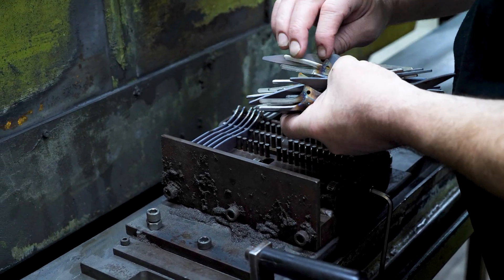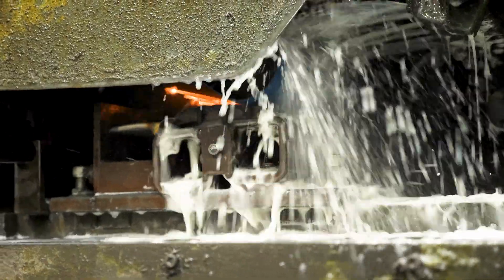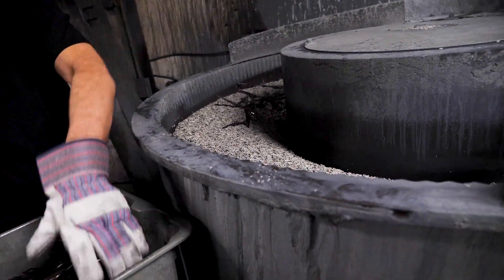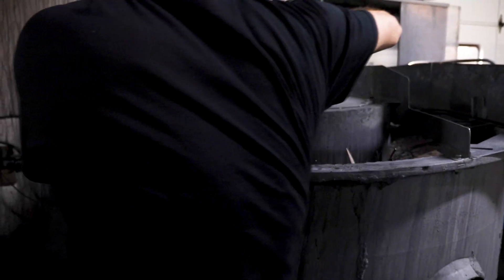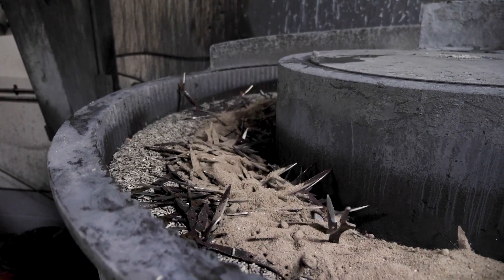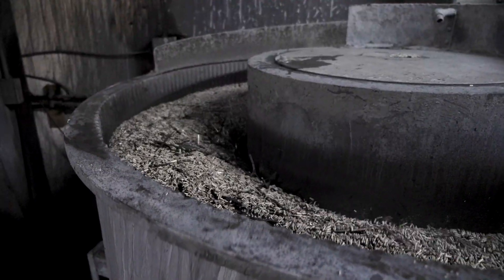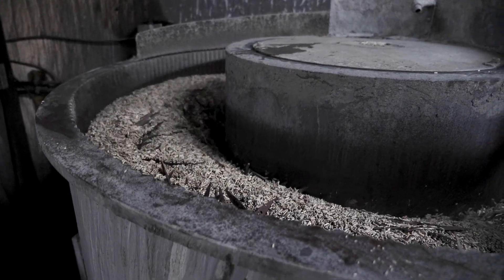After cooling back to room temperature, the blades are taken to a machine that adds a cosmetic grind to the surfaces that are not either a cutting edge or covered by a handle — grinding the leading edge and the back spine of the blade. From there, the blades are loaded into a vibratory tumbler to give them a nice shiny polish. The media is three-millimeter-thick ceramic and we add an abrasive compound. The cycle runs for 16 hours; the compound starts out fairly abrasive but as it breaks down it gets finer and finer, ending up giving that nice mirror finish. This process also helps to remove additional burrs and radius all the edges.